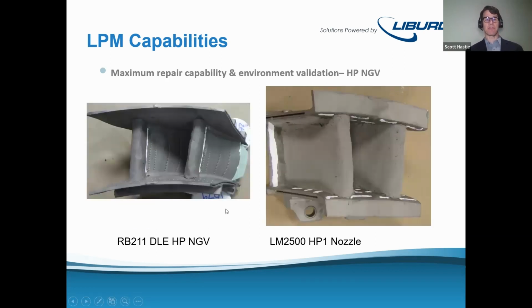This is the next step for both vanes. Now we've applied the LPM on the leading edge, and it is just like what I said. It's putty. It's superalloy contained in some solvents as well as a plasticizer to be able to get it to stay in position as we run it up to temperature in consolidation. And we've done the same thing on the LM2500 HP nozzle here, but to a much greater extent, in that we're doing a full wall thickness repair across that entire surface, and then repairing each one of those groups of cooling holes all the way through. The white you see there is just a stop-off, to keep a group of cooling holes adjacent to the repair surface open during the repair, so we don't have to do additional machining that's not necessary within the work scope of the repair.